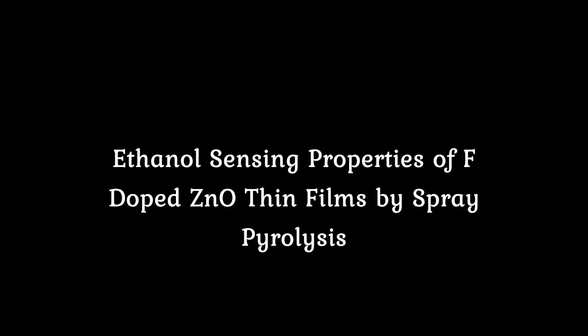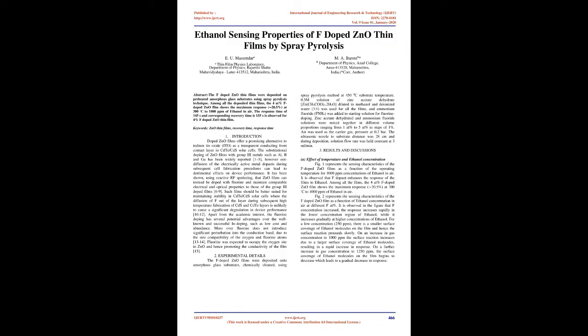Ethanol sensing properties of F-doped ZnO thin films by spray pyrolysis. Abstract: the F-doped ZnO thin films were deposited on preheated amorphous glass substrates using the spray pyrolysis technique. Among all the deposited thin films, the 4% F-doped ZnO film shows the maximum response, 20.5%, at 300 °C to 1000 ppm of ethanol in air.